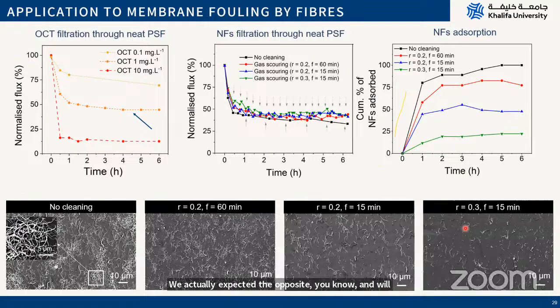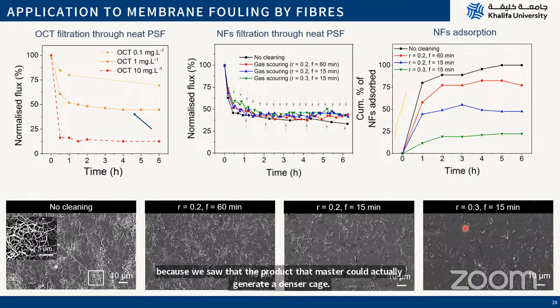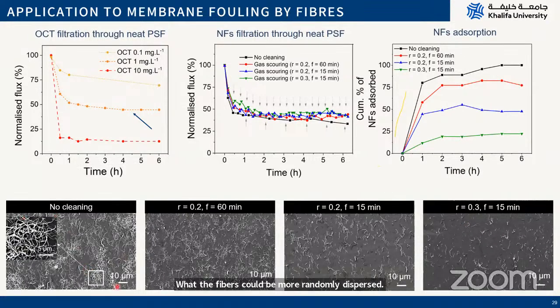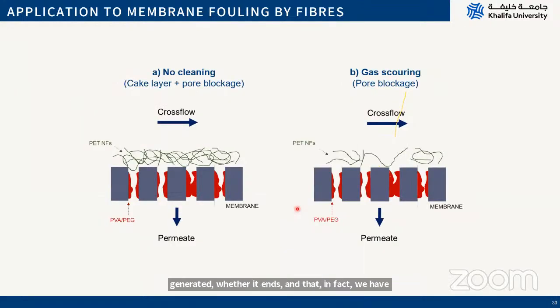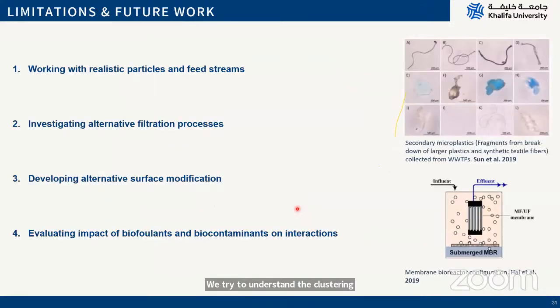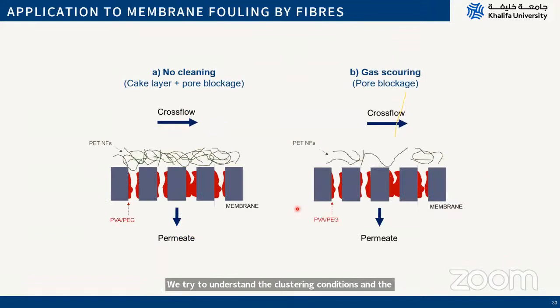We thought that the particulate matter could generate a denser cake, while the fibers could be more randomly dispersed. But in fact, we found that the clusters being generated were very dense, and that we had lots of alignments generating much tougher clusters overall. Again, we try to understand the clustering conditions and the cake layer formation across the systems to better predict the impact of the fiber diameter and also the long-term performance of the system.